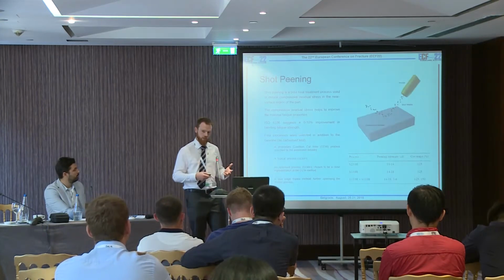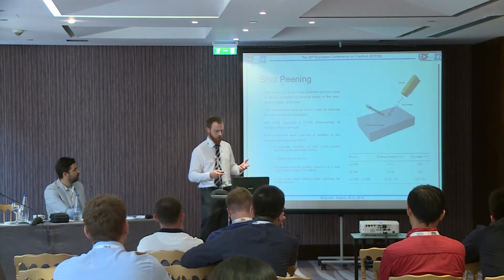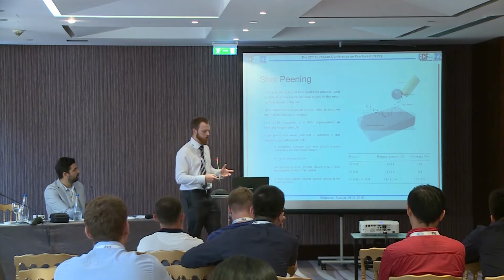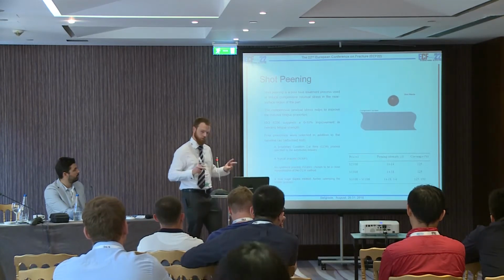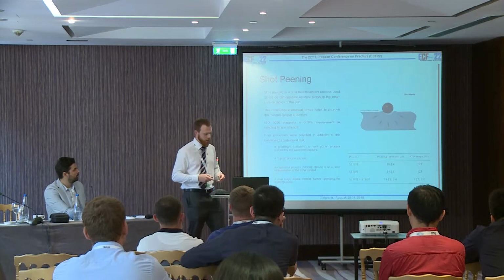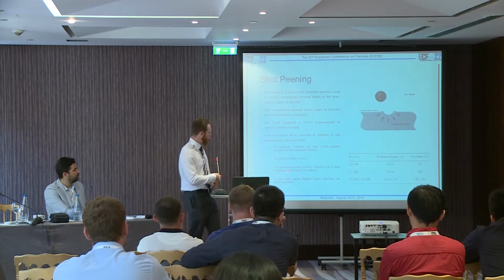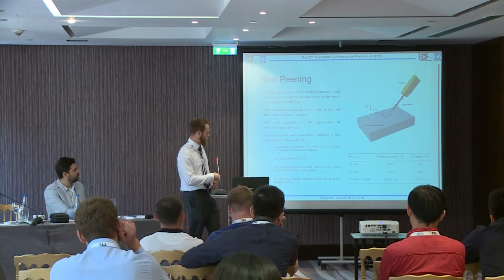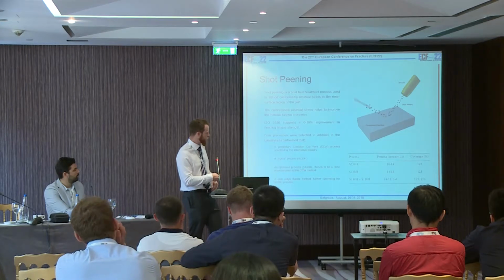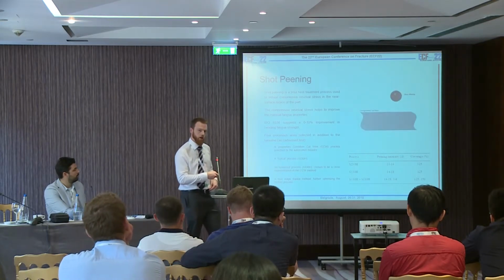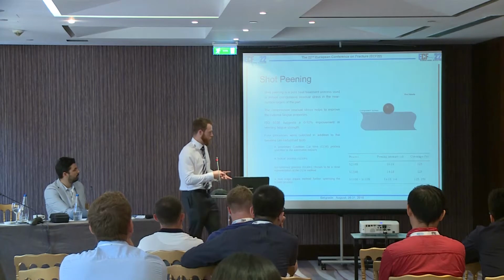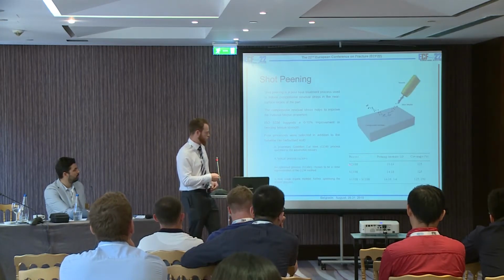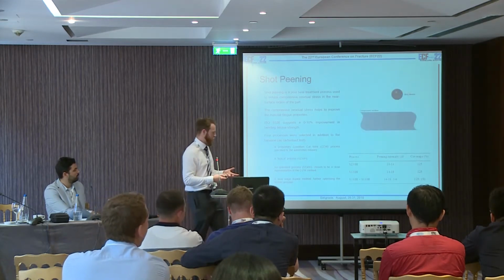The other three processes were commercial processes using cast shot. The first being what the industry calls a typical process. The second being a slightly larger shot size, and this was chosen to be as closely representative of the conditioned cut wire process that we could go to. So I can't give you the details of the conditioned cut wire process, but the 330H process is close to that. It's an optimized process.